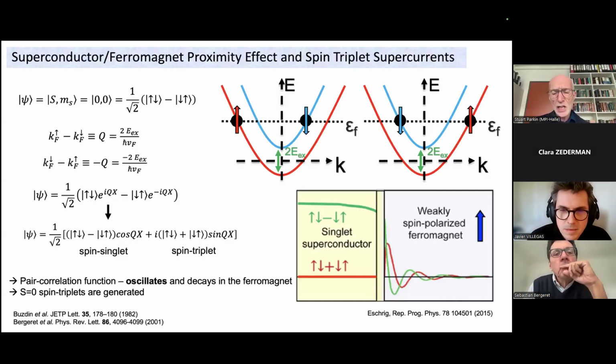And at the same time, as you can see in this figure taken from this review article by Eschrig, the green singlet state would decay into the ferromagnet in an oscillatory fashion, and similarly the triplet state would be formed in the ferromagnet and would also have this oscillatory decay. Typically in the ferromagnet, this superconducting wave function would rapidly decay. However, if you make the ferromagnet very, very thin, then you will have a superconducting wave function that persists.